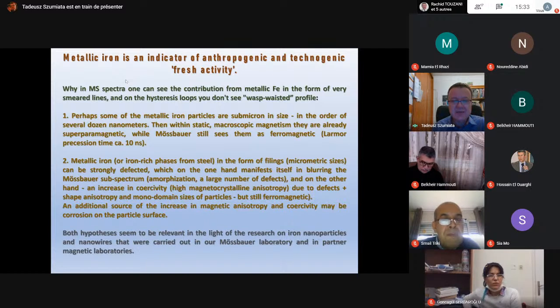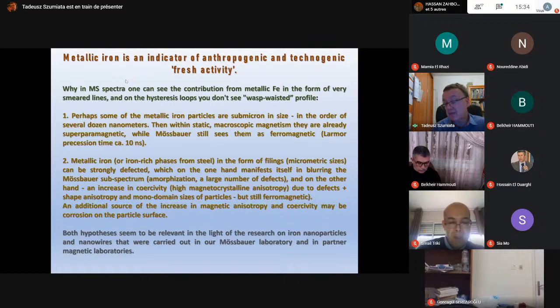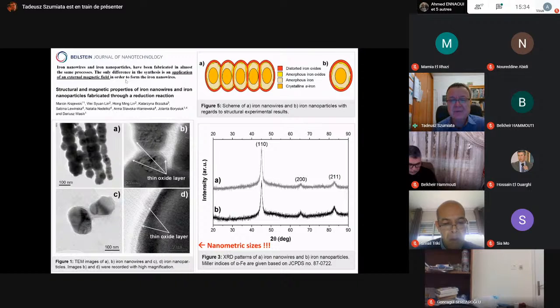And another reason could be the plenty of defects in such small metallic iron of technogenical origin inside the dusts, and such defects could enlarge magnetocrystalline anisotropy and elevate the value of the coercivity. That's why the coercivity of usually soft iron could be very similar to the coercivity of dominating magnetite. And we have found the confirmation of such suspicions.